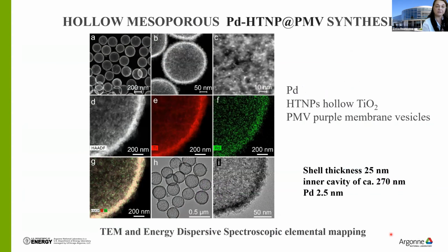So everything started from synthesis. We start from synthesis of mesoporous hollow titanium dioxide cages, through first synthesis of silica nanoparticles and then deposition of titanium dioxide on the surface of the nanoparticles. Then we removed the template. Actually, I do not see my presentation now, my screen is getting dark for some reason. But yeah, then we also deposited palladium dots on the surface of these cages, and we also modified the surface through aminosilane chemistry to have positive charges.